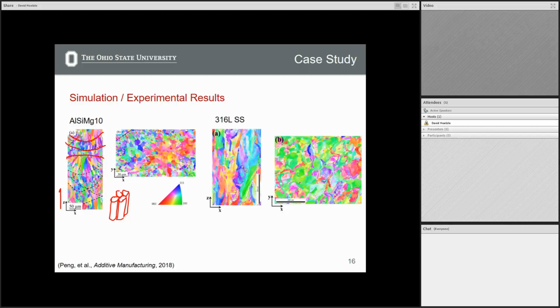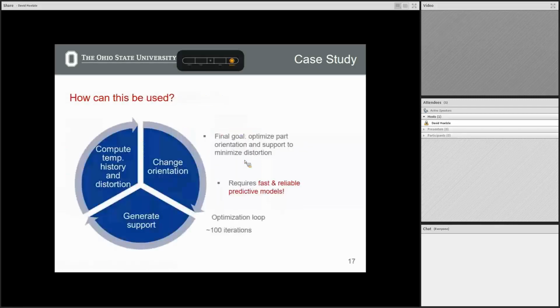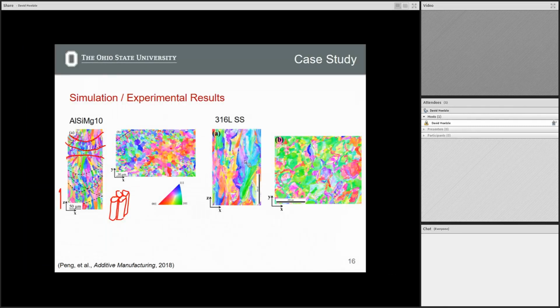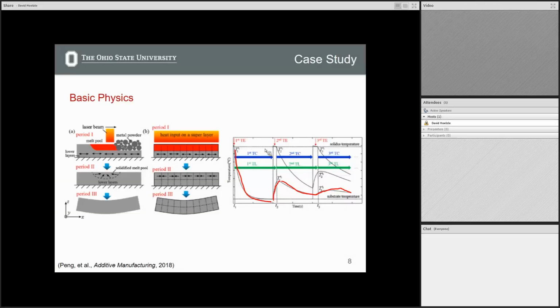Okay. All right. So then this is, I guess, I would say more of a scientific study. And then the question is, where can this potentially be used? And so how we've used this information, I kind of glossed over it at the beginning, but if you look at our models for residual stress buildup, this temperature profile, we were investigating very, very efficient ways to try and get this temperature profile. And then we were also looking at quasi-static analysis, assuming that this material is freezing into place at only distinct periods in time.